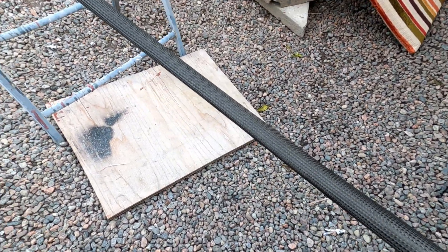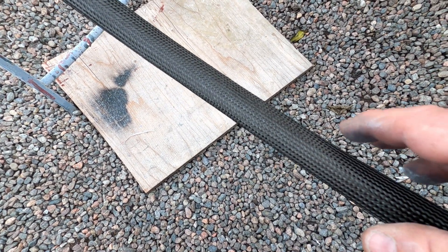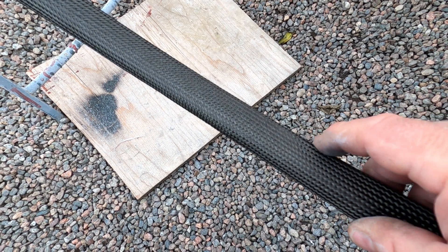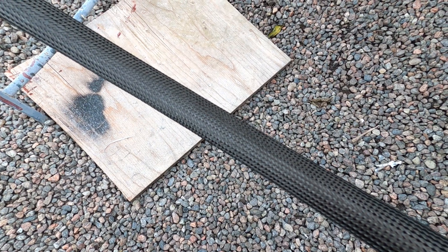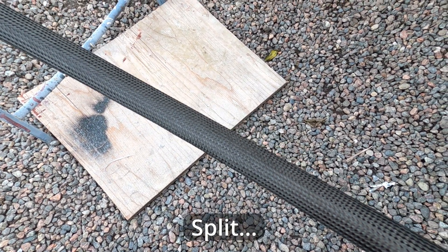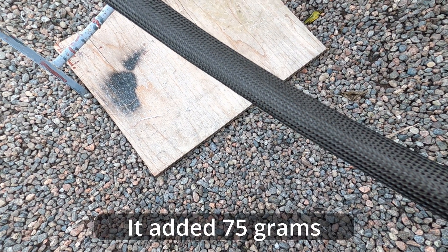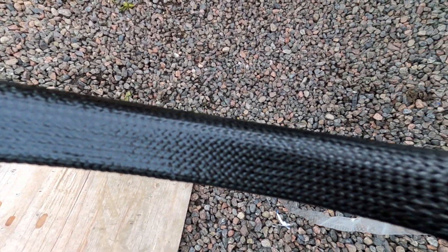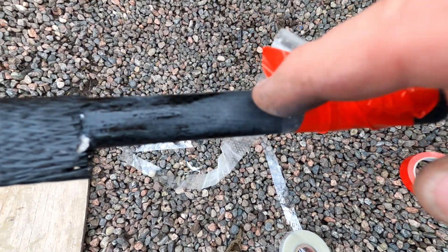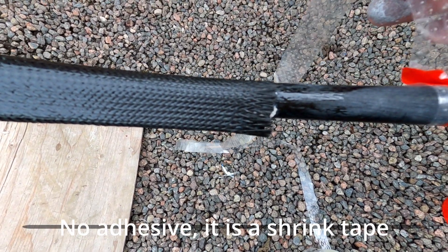Change of plans — I'm putting one of these carbon fiber socks over the mast. I just realized the section where I'm going to have my sail track is pultruded, and I'm afraid it will crack if I don't reinforce it. This will add a little bit of weight to the rig, but I'm going ahead anyway because I'm afraid the sail track won't be strong enough without it. The carbon fiber sock is now wetted down. I'll use this perforated tape — that's why I make the mast a little bit longer — so I can tape this and start winding, then use the heat gun to shrink it.